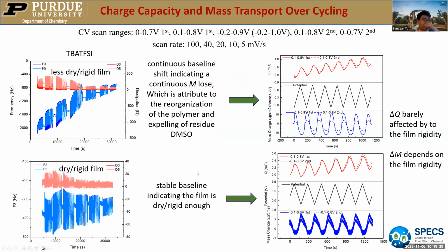So here is the thing: when I do a long time of CV cycling, about 7 or 8 hours, with different CV ranges. This is, for example, a typical CV I did for this film, with different scan rates for many cycles, because I want to understand its stability. We can see the dissipation and the frequency oscillate during all this cycling.